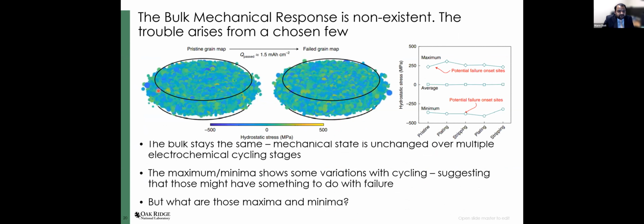failure. If you look at these two images, they are the grain maps and the hydrostatic stress of each grain plotted for the pristine sample and the failed sample. And you can see that this average essentially remains 0. What fluctuated was in fact only the maximum and the minimum. On average, the 30,000 grains that we imaged in a pellet showed no change. So this was fundamentally very interesting to us.